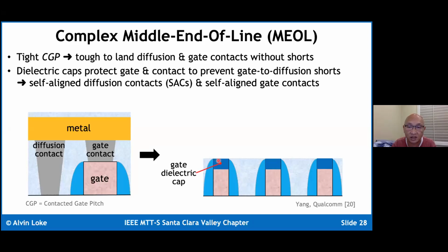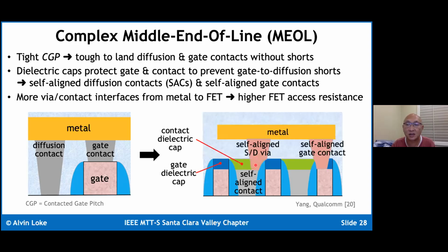So for instance, after we do our contact dielectric and polish, it's not uncommon to grow a protective gate dielectric cap, which allows us to incorporate a self-aligned contact, which if misaligned, will not short to the gate because there's a protective cap there. Furthermore, it's not uncommon that you would want to protect the self-aligned diffusion contact with a dielectric cap, because then as you do subsequent self-aligned gate contacts, you need to make sure that the self-aligned gate contact, if it's misaligned somehow, is not going to inadvertently short to the diffusion contact.